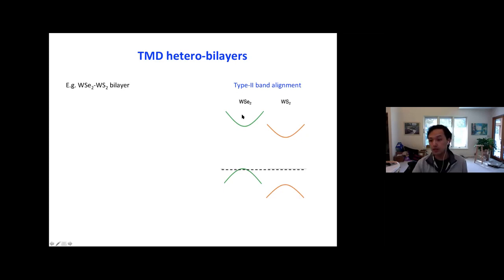In this case, we make a TMD hetero bilayer. For instance, WSe2 on WS2, these are two different materials. And if you don't do anything specific, if you don't try to angle align them, then they will form something called a type 2 band alignment in semiconductor heterostructure, which looks something like this, that the conduction band of the WS2 layer is the lowest energy, and the valence band of the WSe2 layer is the highest energy. Okay, so that's why it's called a type 2, because one belongs to one layer, the other belongs to the other layer. And the dashed line is the Fermi energy, which typically in experiment can be tuned by gates.